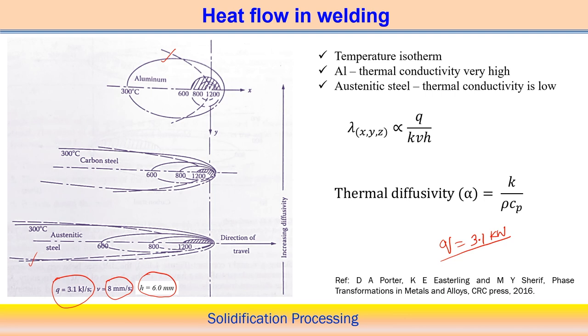Now, it's a more oval shape. In this case, if it is a spot welding process, spot welding means velocity equal to zero, then we can expect the profile to be exactly circular. So similarly here also the profile can be circular, but the radius of the circle for a particular isotherm should be different in these two cases because thermal conductivities are different.